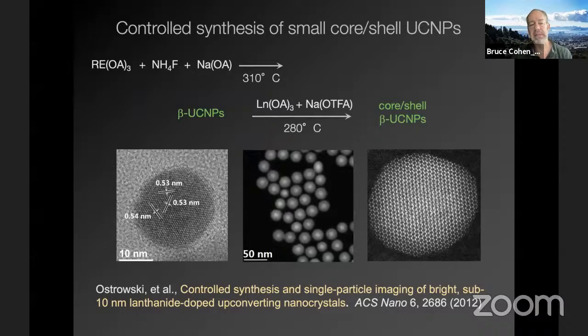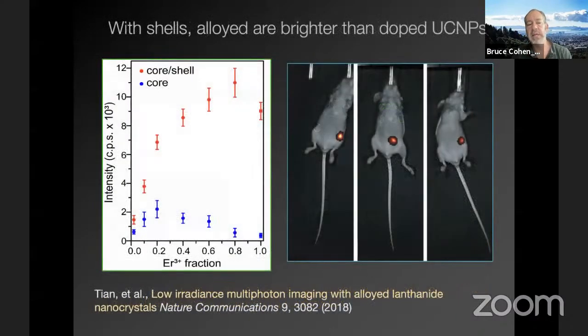And this set in motion a lot of our other work in trying to improve these materials so that you could image them at very, very benign conditions. So we would do single particle characterization, varying the amount of lanthanide in the nanoparticle, all the way up to 100% doping. We started calling these alloyed nanoparticles, and we showed that you could image these several millimeters into tissue.